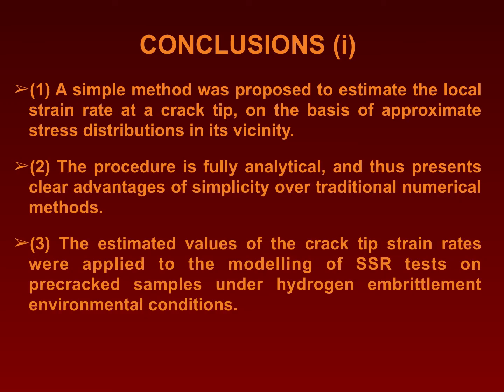A simple method was proposed to estimate the local strain rate at a crack tip, or crack tip strain rate, on the basis of approximate stress and displacement distribution in its vicinity, the crack tip stress and displacement fields. The procedure is fully analytical, is approximate on the basis of linear elastic fracture mechanics principles, and thus it presents clear advantages of simplicity over traditional numerical methods.